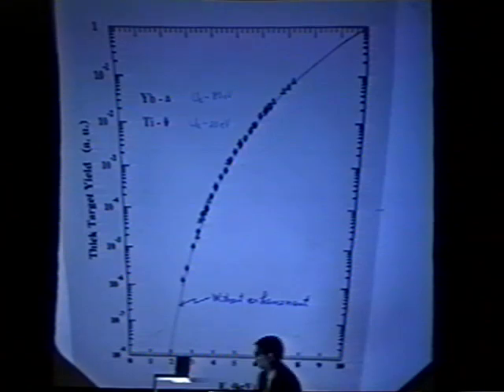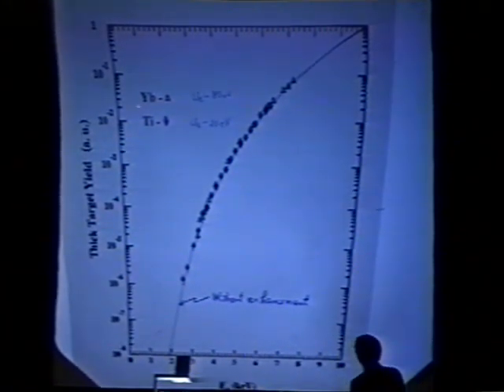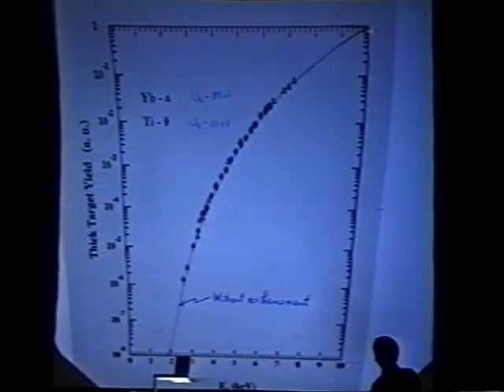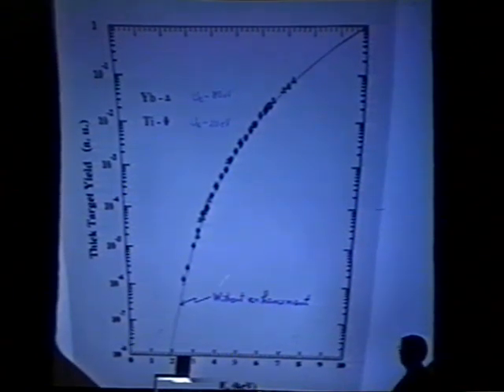Okay. Since I don't have so much time, I will just go to the results. This is the result which I already reported at the last conference for the deuterium and titanium case. The green is deuterium and the blue one is titanium. As I said, these yields are normalized at 10 keV. And you see a very quick decrease of yield as the deuteron energy is lowered. The dotted line shows the standard predicted yield, that means without any enhancement. Well, actually, these two data sets just follow this line, though I said that there is a little enhancement.